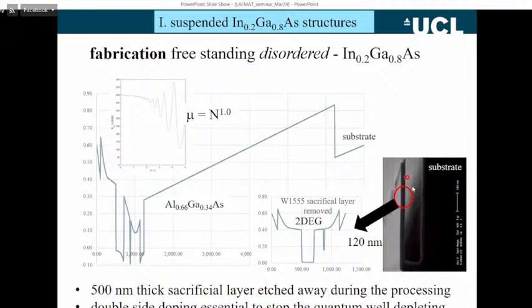And if you put this structure in an SEM, so the image on the right here is an SEM image, you can see where the etch has completely undermined this sacrificial layer, and we're just left with this freestanding structure, which is 120 nanometers. So we can make these things 120 nanometers.